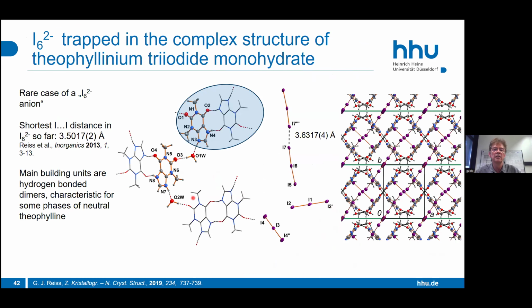And also, in this case, we have a compound which contains some additional water. And then we have, again, these hydrogen bonded dimers of the cations. Then we have a water molecule. And the interesting case here is that we again find such an I6 2-. It's sometimes strange. Until 2000, nobody had published I6 2-, and then not just we alone. Many other people have published some of this I6 2- since then.